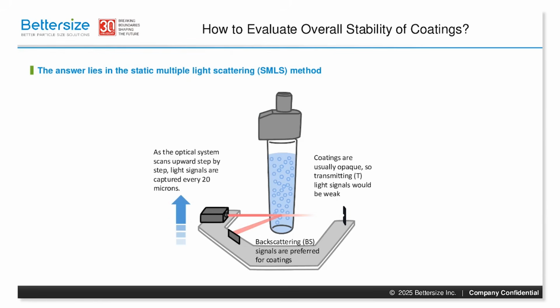How do we analyze the stability of coatings and other suspension systems in general? Static multiple light scattering, or SMLS, is a powerful, non-destructive, simple, and fast technique. As you can see, SMLS shines a light source on the sample, and the resulting light is collected by detectors. The whole optical system scans across the sample, collecting resulting optical signal data over time. Usually, an SMLS instrument provides both transmitting and backscattering optical signal data. Because coatings are typically opaque, transmitted light signals are often weak, making backscatter light a more reliable indicator of changes within the sample. Therefore, backscatter light is preferred for the SMLS analysis of coatings.